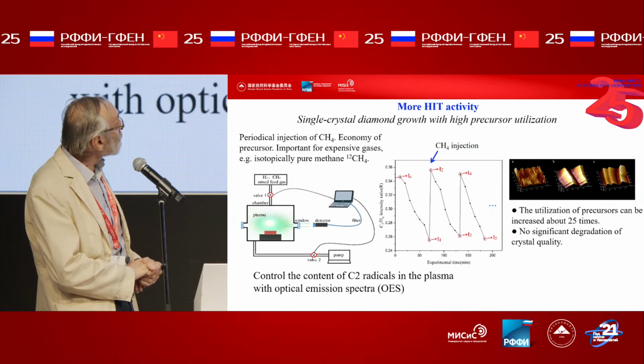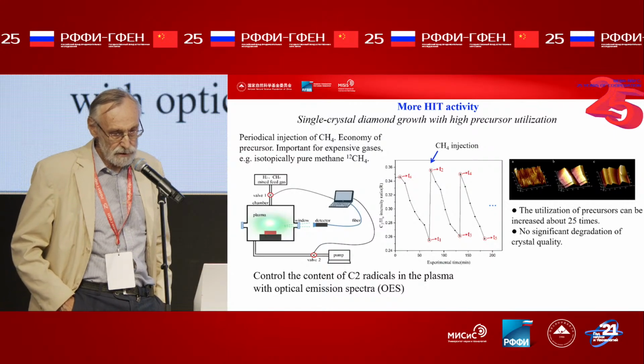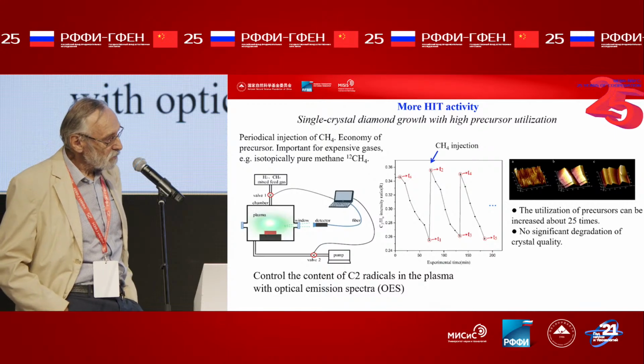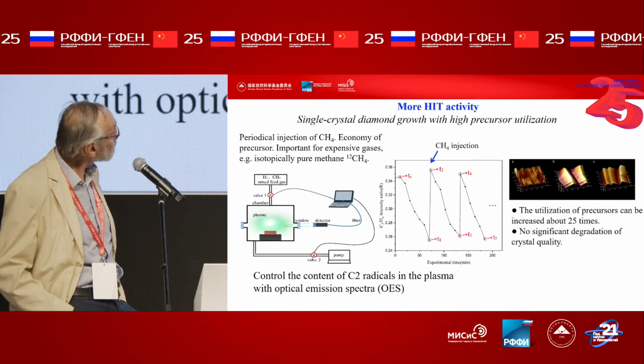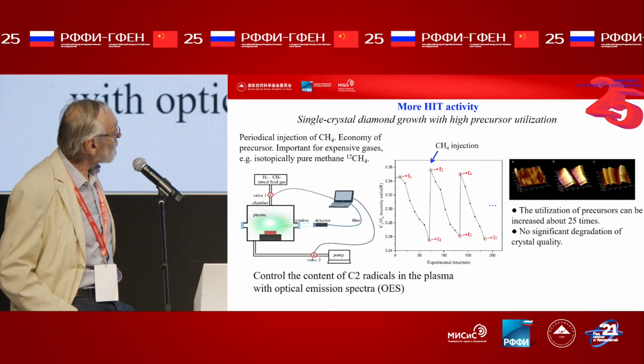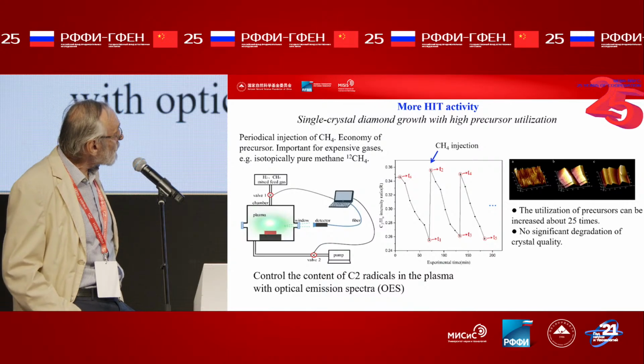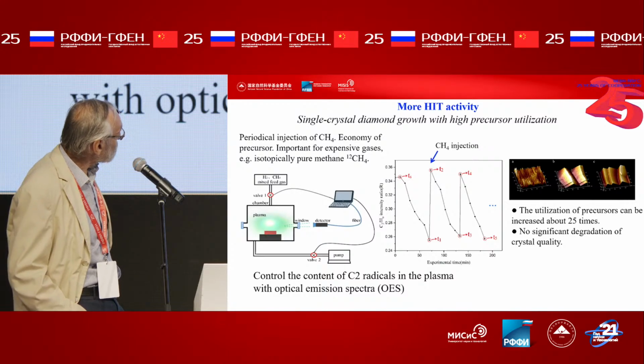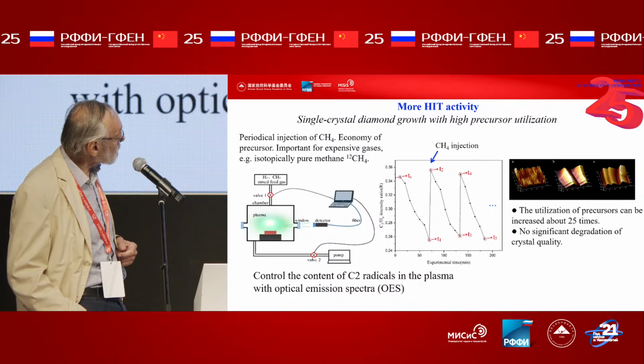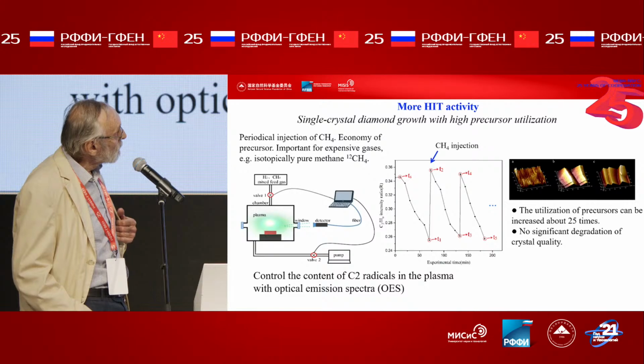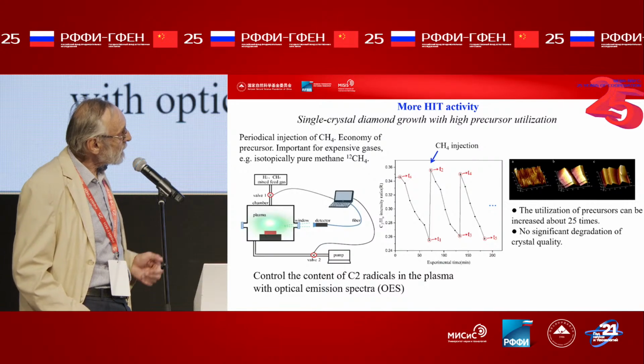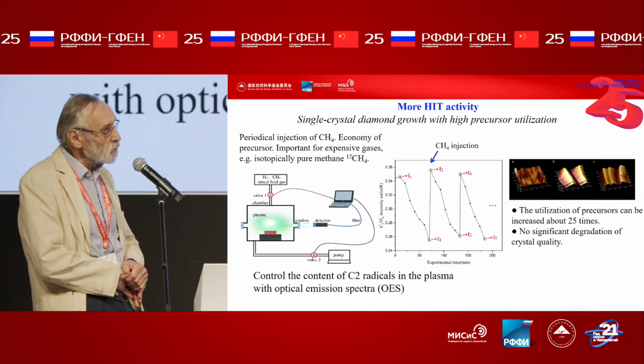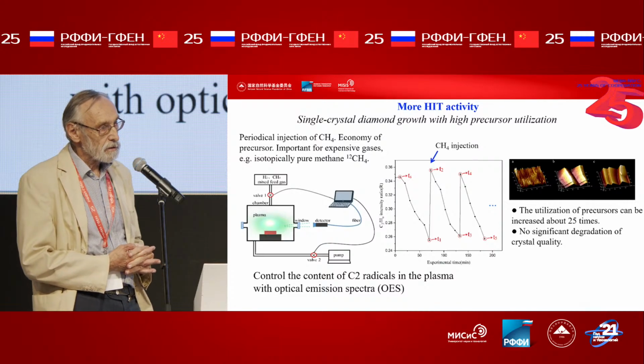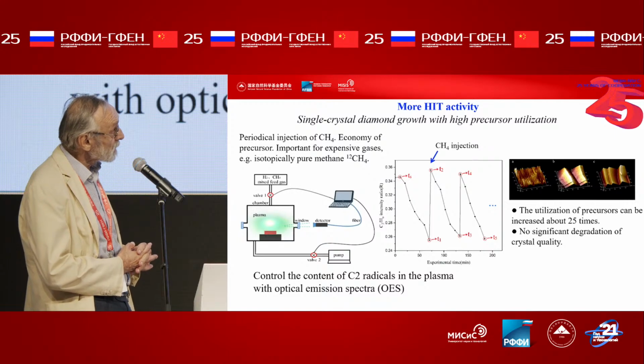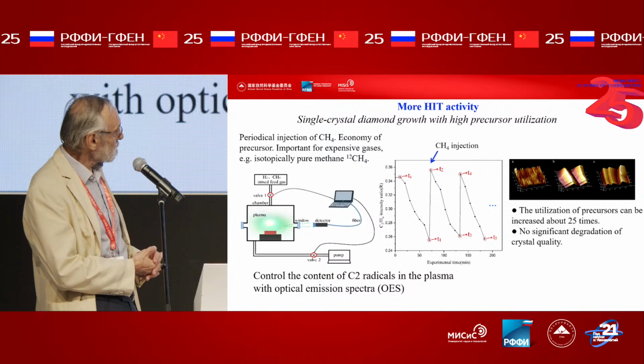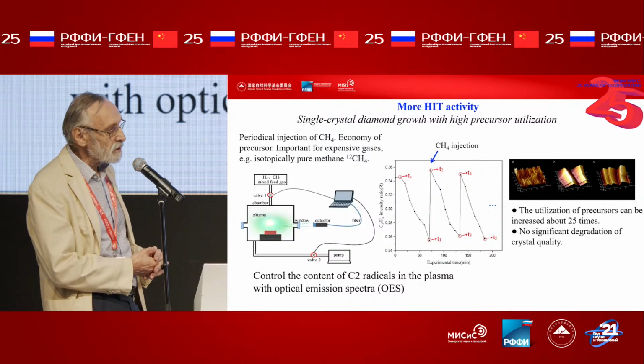Next slide. And another interesting result from the HIT group is that they realized the idea of injecting methane periodically inside the chamber, and monitoring how much carbon they have in the chamber at each moment. The carbon concentration decreases with time, and then they inject the next time. So the gas economy is very important when people use very expensive gases such as isotopically purified methane. The economy is about 25 times, as they measured. So a very original approach.